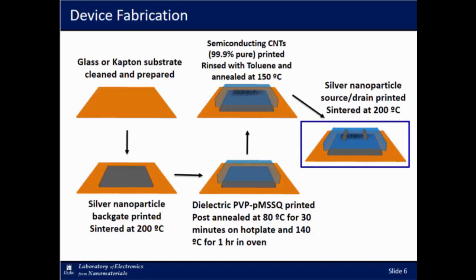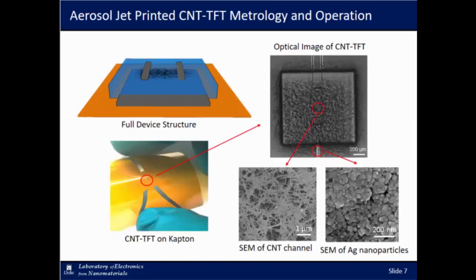So now we have all of our transistor components, and all of them are fully printed. So here's a snapshot of what the device looks like. We have the full structure as well as a photograph of the transistor itself. The big silver nanoparticle things you see in the photo on the bottom left are just to make it a little bit easier to contact. The actual device area, the device length is 150 microns, the device width is 500 microns, and the dielectric square that I printed was 1 millimeter by 1 millimeter.